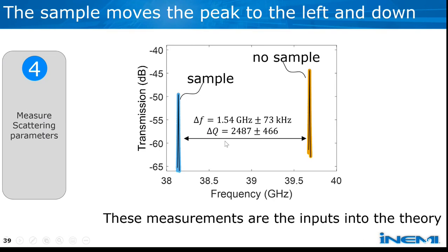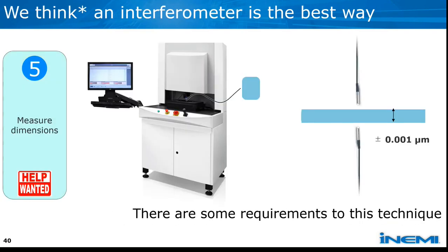So we measure how much it goes down and how much the quality factor changes. So here you can see that our resonance frequency is shifting by about 1.5 gigahertz, and the quality factor is changing by about 2,500. So these are essential inputs that go into the theory and allow us to extract the material properties. Go ahead, next slide.